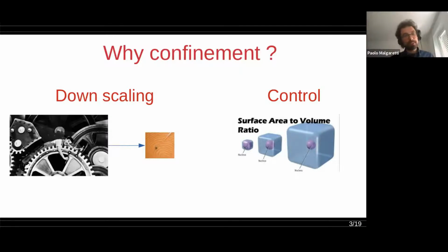So in practice, this is perturbing the system. This, if you want, is the negative side of the story. You can also tell it in a positive way: by controlling the surface of this container, you may aim at controlling what's inside. So in practice, instead of changing the molecular properties of your system in order to induce, for example, a phase transition at a given temperature, you keep the system as it is, but you confine it. Or by confining, you can prevent a phase transition. Nano-confined water doesn't freeze at -2, -3, -10, -15 Celsius, pretty much because of the confinement, because of the interaction with the walls that confine it. So it's also a chance of controlling. On the one hand, it happens in the process of miniaturization. On the other hand, it is a chance to control.